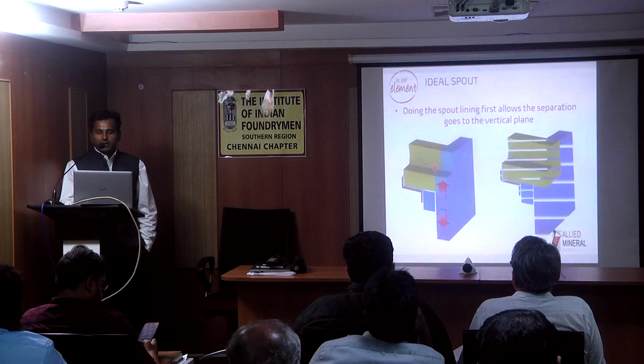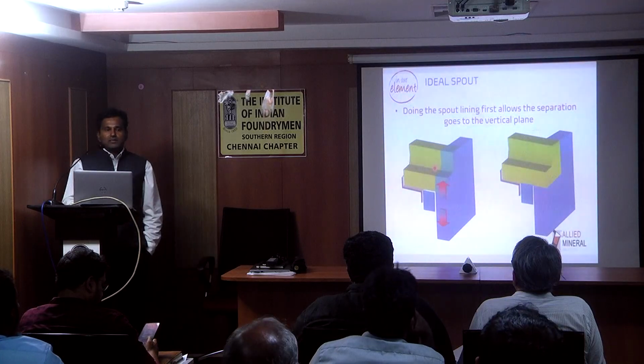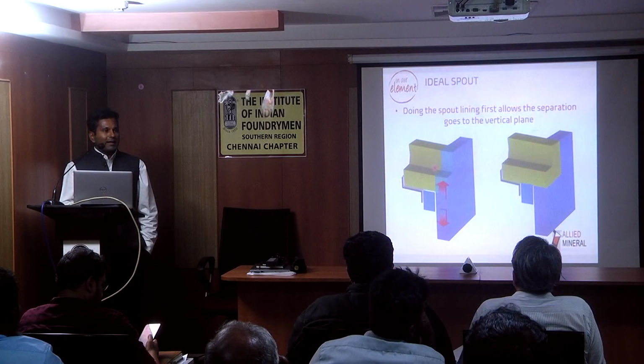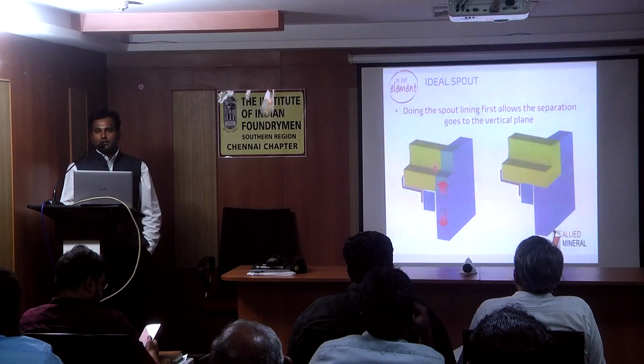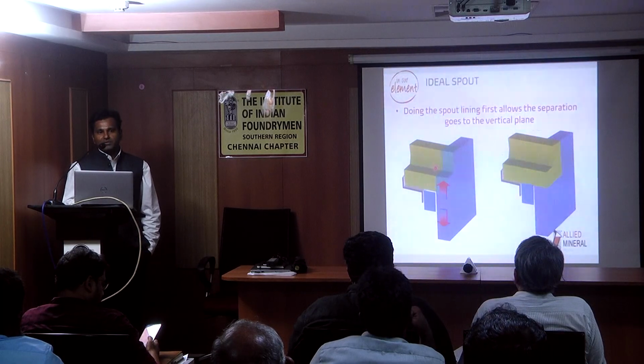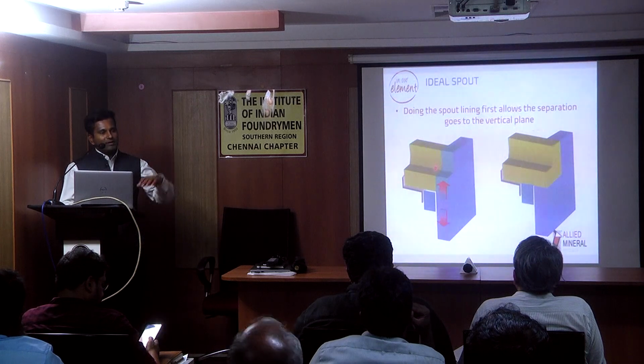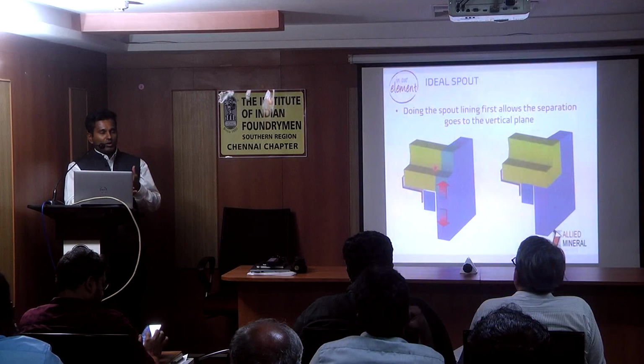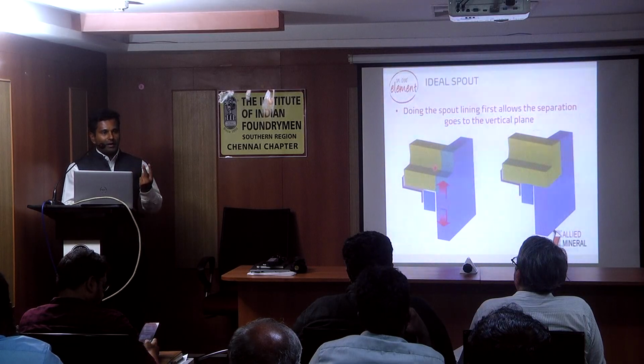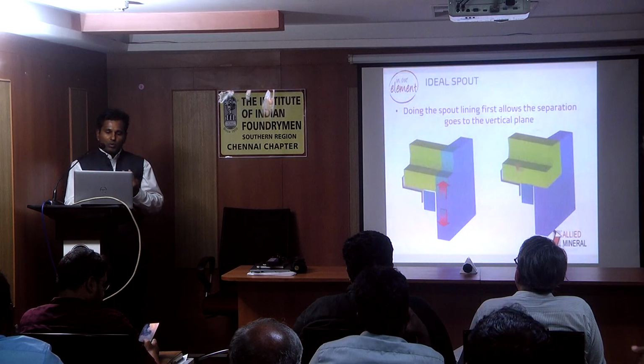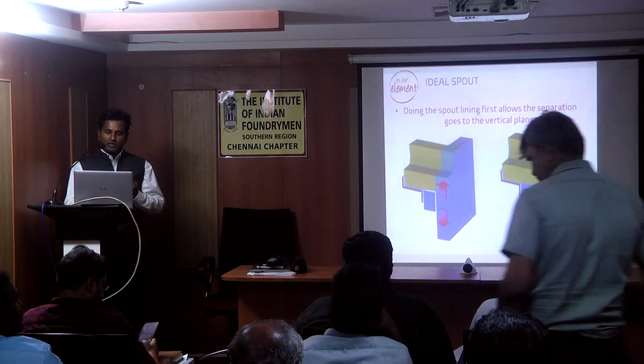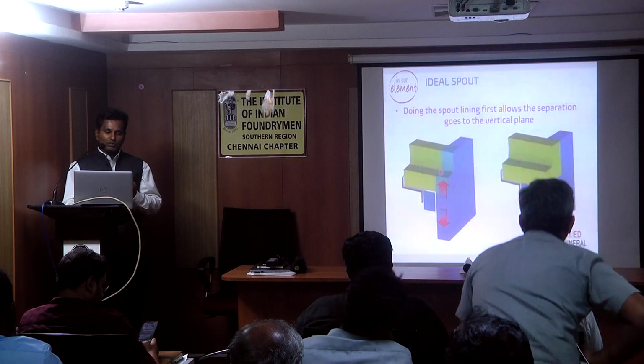The second thing is the spout lining. Generally, the spout is lined with a different material than the working lining. Either sodium silicate or some other binder will be added, and it will be placed after doing the lining. We recommend doing the spout ahead of the lining. It gives you two advantages. One is that your joint is shifted from this particular location to this location.